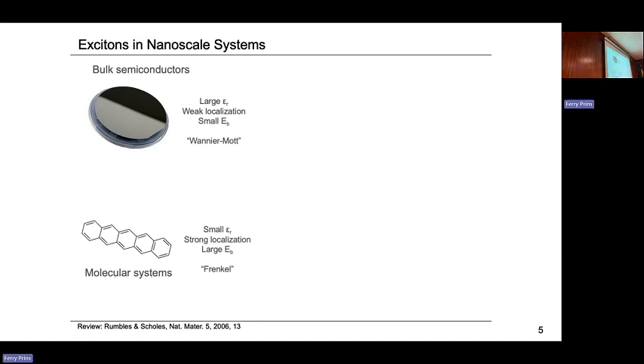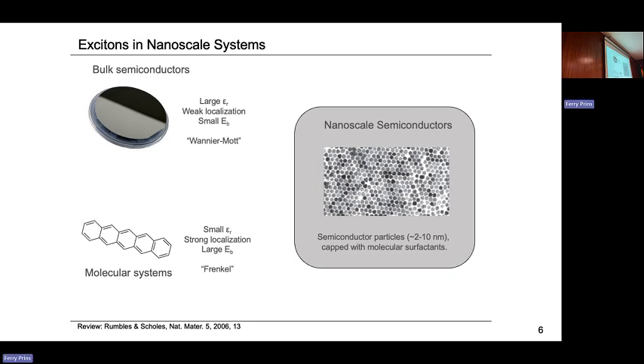When we go to nanoscale semiconductors, it's a little bit weird because we're dealing with these kinds of materials. We have a large epsilon because it's still the same material—we just make it smaller. But now, because we make it smaller through quantum confinement, which I'll get to in a second, we're actually getting large exciton binding energies. So we have packages of energy which are typically excitons, but they are living in this environment with large epsilon. It's a little bit weird, so there's going to be different physics going on here.